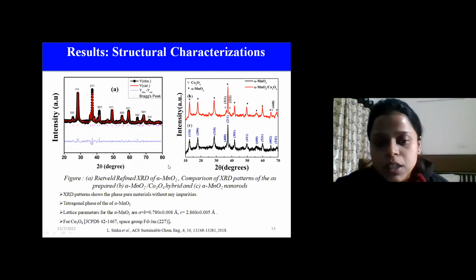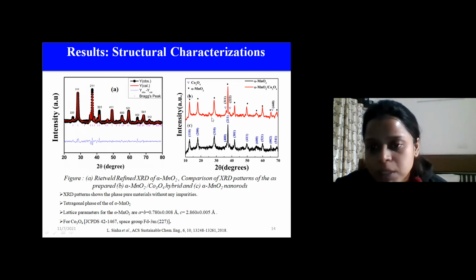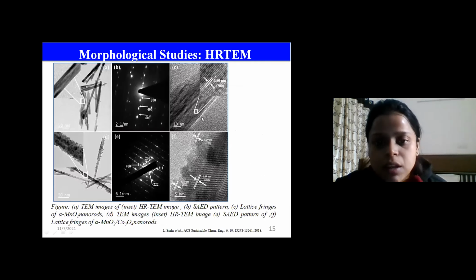So first, for confirming the structural properties, we have done the XRD, and we can see here that the material is pure. We have also conducted the Rietveld refinement so as to know the other lattice parameters of the material, and it has come as a tetragonal phase of the alpha MnO2 nanorods. Then we have also conducted the XRD of the alpha MnO2 Co3O4 hybrid nanomaterial, and we are seeing that the material is in pure phase.